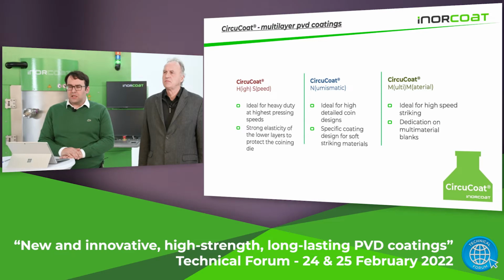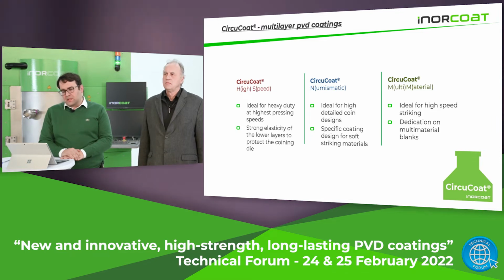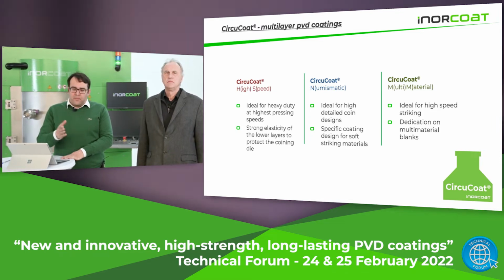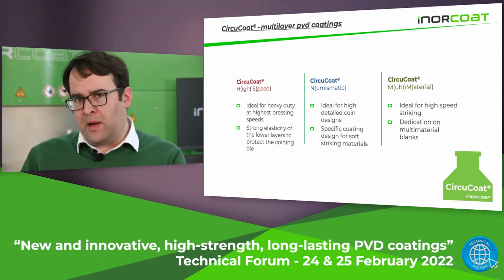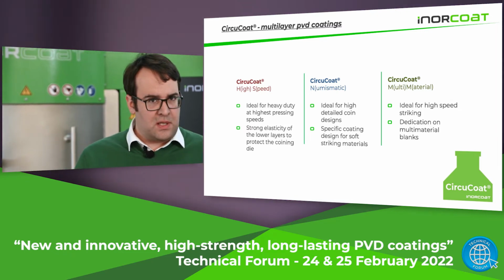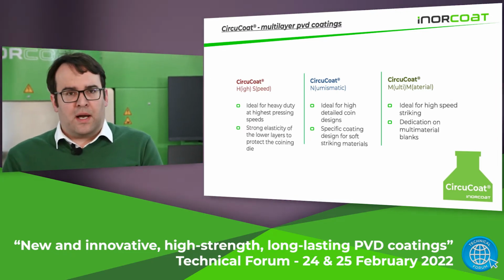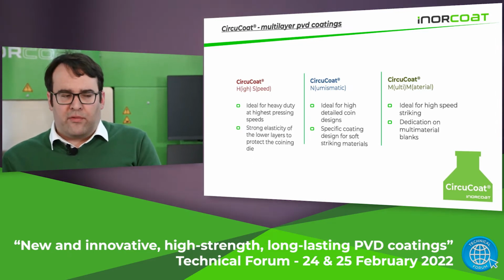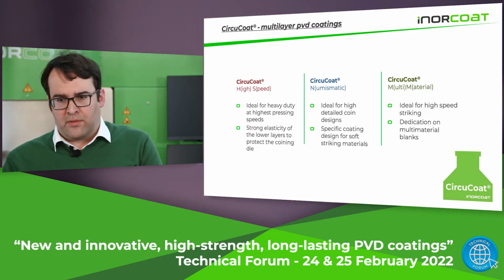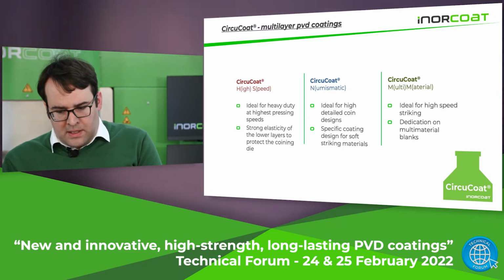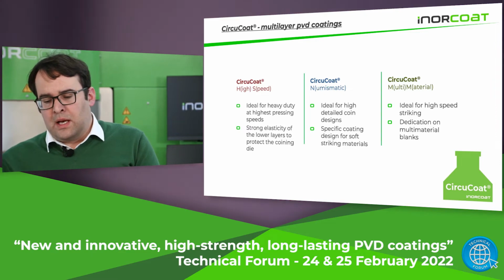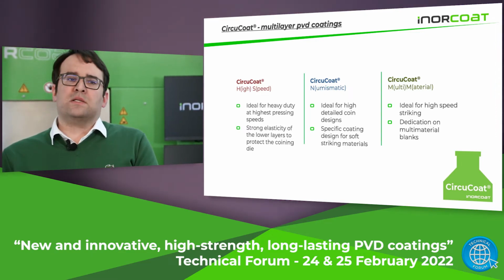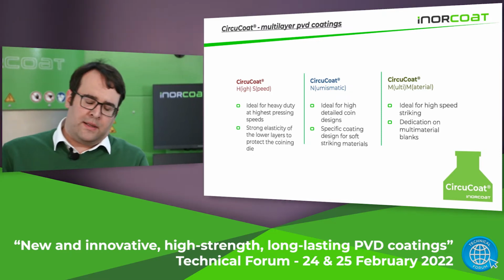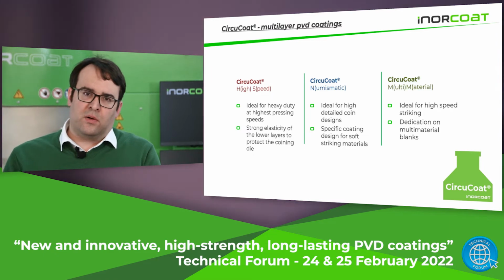So what have we done? As I mentioned, we developed together with Professor Martin Andritschky this new group of coatings. As you can see on this slide, we have developed 3 variants, which are all based on the same elements. On the one hand, CircuCoat high speed. So high speed, high S means for circulation coins application, where you have a high speed of striking, where strong elasticity of the coating is needed. The second one, as mentioned, based on the same elements, is CircuCoat N. N stands for numismatic. This is a coating which has been adapted for soft striking materials like gold and silver.